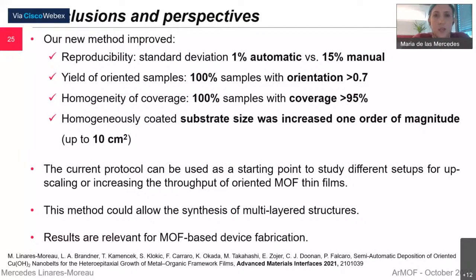So basically, some conclusions: we were able to improve the reproducibility substantially from a 15% variation in the orientation with the manual procedure down to 1% variation with the automatic protocol. We had 100% of samples with a high orientation above 0.7 and also all of the samples with coverage above 95%. And we were able to increase the substrate size that could be coated.